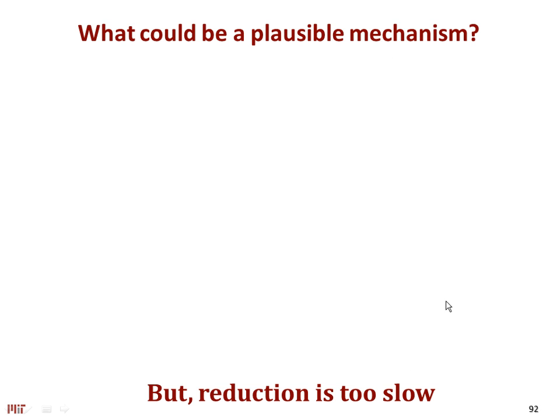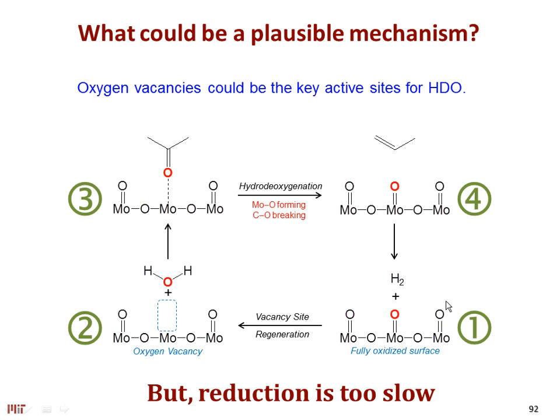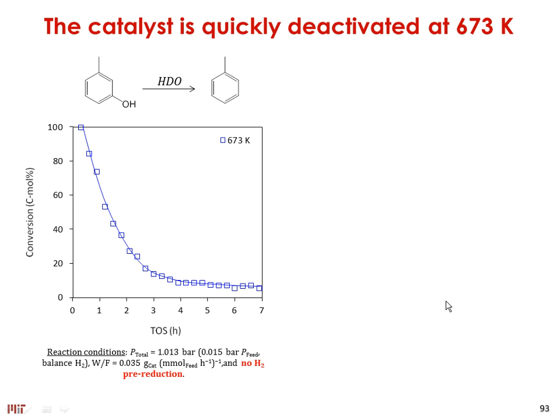But if our catalytic system, if vacancy creation by reducing with hydrogen is actually involved in our rate determining step, so kicking out this oxygen from here should be very relevant in our mechanism. But when we look at the transition from molybdenum trioxide to molybdenum dioxide, the reduction is actually slow under this condition. So we know that there's something else going on. This vacancy generation cannot be the only thing explaining the kinetics that we see. So we're still investigating that.